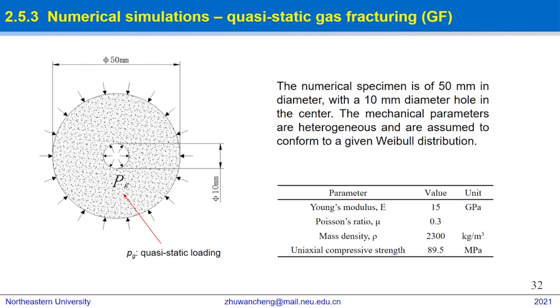This slide shows the numerical simulations of quasi-static gas fracturing. The numerical specimen is 50 mm in diameter, with a 10 mm diameter hole at the center. The rock is assumed to be heterogeneous, with its Young's modulus and strength specified according to a Weibull distribution with the parameters as listed in the table.